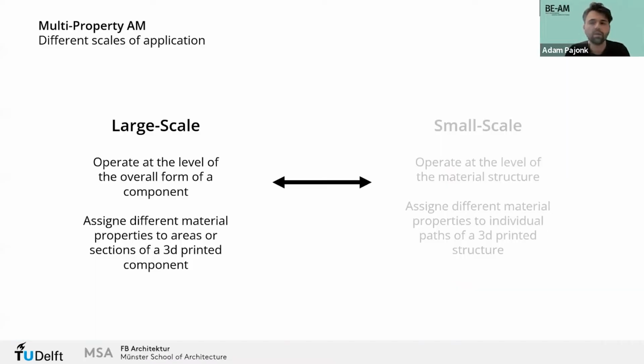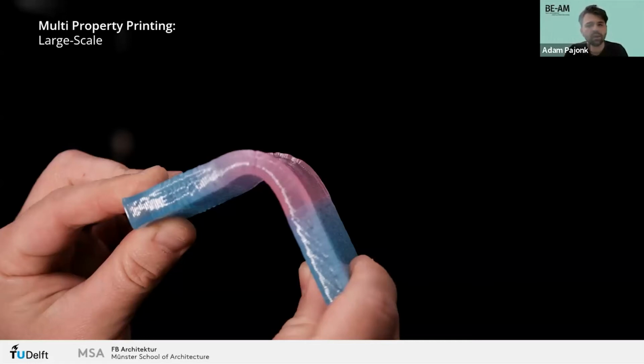throughout the printing. So moving on, after defining these possible properties of the setup, we looked into ways of applying multi-property 3D printing. And here we start to describe two different scales on which properties can be implemented. First, on a large scale, where we operate at the level of the overall form of a component and assign different material properties to whole areas or sections of the 3D printed component. Such as, for instance, with these implemented movable joints, where we can create this moving without any form of assembling, but just by changing the composition of our polyurethane material.